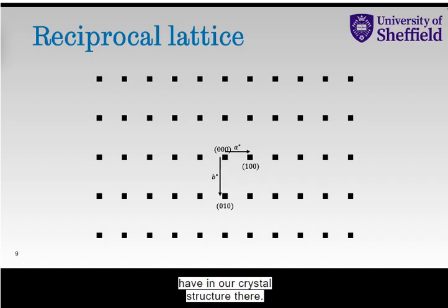So if we have a crystal, what we have now shown is that we're going to get diffraction restricted to key points that are defined by the reciprocal lattice. So a crystal structure will produce a diffraction pattern that has diffraction only in certain discrete spots, certain discrete diffraction beams, which we can define by the reciprocal lattice shown here.